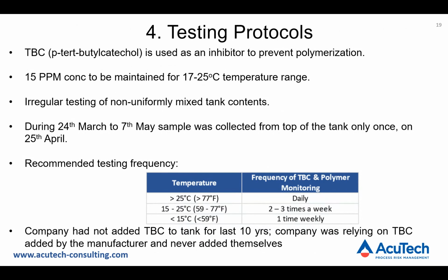Due to the change in the circulation system and loss of mixing, samples taken were not representative of the bulk contents of the tank. It should be noted that the plant had not added TBC to the tank in at least 10 years. Due to the high turnover of material in the tank and the addition of TBC by the vendor to the deliveries, there wasn't a concern about the TBC depletion under normal operating conditions.